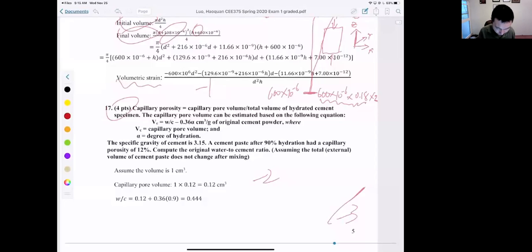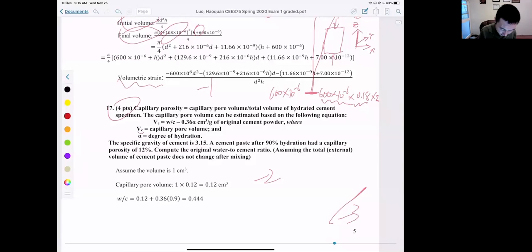The capillary pore volume equation is shown here. VC is the volume of capillary pores, which is a function of water-cement ratio and degree of hydration alpha. The question also tells us the specific gravity of cement, degree of hydration 90%, and also the porosity of 0.12. So calculate what is the water-cement ratio here.